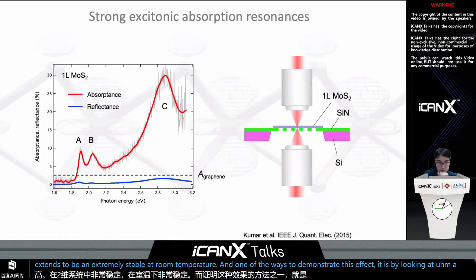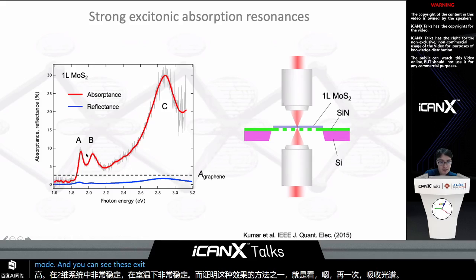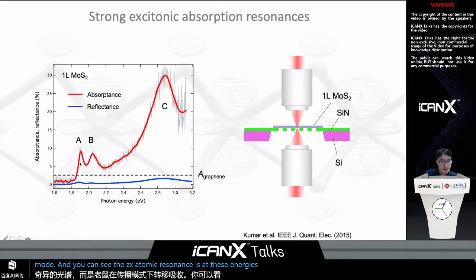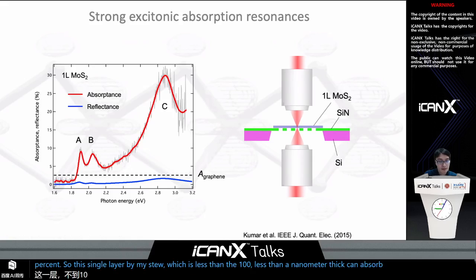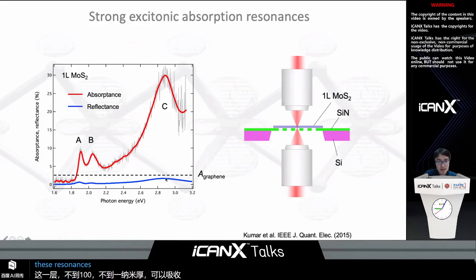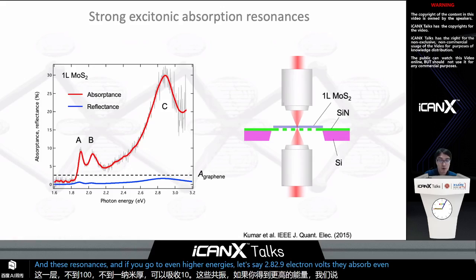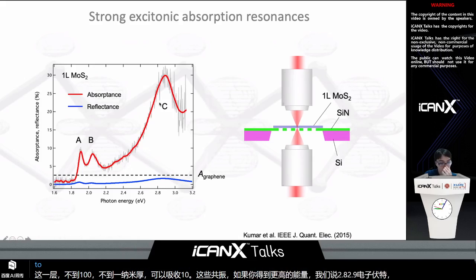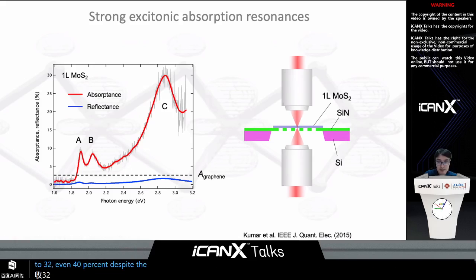And one of the ways to demonstrate this effect is by looking at, again, the absorption spectrum. So this is an absorption spectrum of a single layer MoS2, in transmission mode. And you can see these excitonic resonances at these energies, and these excitonic resonances give you absorption of close to 10%. So this single layer of MoS2, which is less than a nanometer thick, can absorb as much as 10% at these resonances. And if you go to even higher energies, let's say 2.8, 2.9 electron volts, they absorb even more strongly, up to 30 to even 40%, despite the fact that they are less than a nanometer thick.